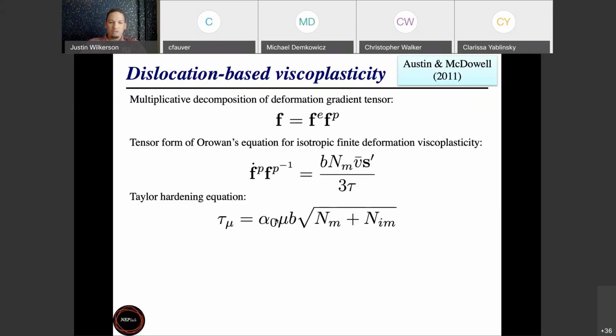In addition to that, we have a hardening relationship, the Taylor hardening equation, which dictates the hardening of the material. So as I increase both my mobile dislocation density and my immobile dislocation density, then the material will harden. We'll make a distinction here that mobile dislocations are the carriers of plasticity. They're the ones that can move and they create plastic deformation. Immobile dislocations do 2 things. They can be barriers to the motion of mobile dislocations, so they create obstacles. And in addition to that, they contribute to the hardening of the material.